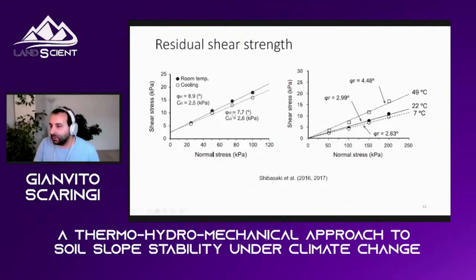And what they noticed was an over 10–15% decrease in the shear strength, over 1 degree loss in residual friction angle, that for a slope that is already unstable really can make a big difference, can remobilize, can speed up an existing landslide. They did the same for a commercial soil. They also went into warming, and they say that the colder the temperature, the weaker is the material in terms of residual shear strength.